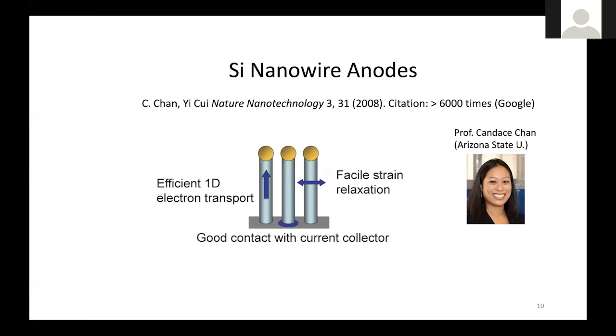About 13 years ago, when I started to work on silicon, we published this first paper using silicon nanowires, growing off the metallic current collector, so you can ship the electrons in and take the electrons out directly. This maintains direct electron contact, and the diameter of the nanowires is small enough that our hypothesis is it could relax the strain fast and will not break. And there's also space between each of these wires for the volume expansion without breaking. So this concept really kicked off the whole research field of using nanotechnology and nanoscience design to impact the batteries field.